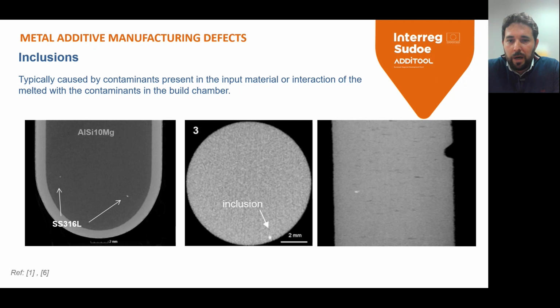Inclusions are normally caused by cross-contamination with other materials, or even can be produced as an interaction with contaminants in the building chamber. Here you can see other examples in the image. This is aluminum powder for laser powder bed fusion with some white spots that are inclusions of stainless steel. This is a solid material with an inclusion close to the border. And this is a digital radiography image where you can see here an inclusion and also some lack of fusion in the material.